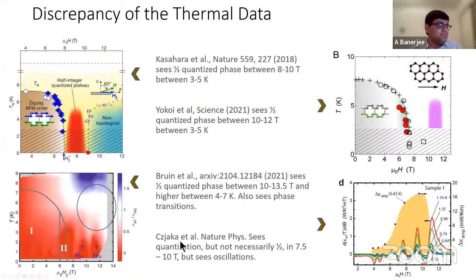And then there is this paper from the Princeton group, in which I am also a co-author, where we showed that at low fields, you basically get this quantum Shubnikov-de Haas type oscillations in the longitudinal conductivity σxx as a function of field. And that's actually a very, very weird phenomenon, because in order to have Shubnikov-de Haas, you need to have a metallic state, but this is an insulator.